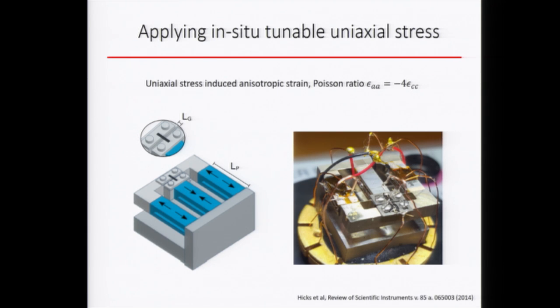For ZrTe5, we're lucky because the crystal naturally grows into a thin needle, and that's the ideal shape you need for this type of measurement. The thinner and the larger the aspect ratio, the more uniform the strain for this uniaxial pulling. Another technique you can use is directly gluing the sample on the side of the piezo stack. For that, you actually want a very square-like sample to get full transmission for each direction.